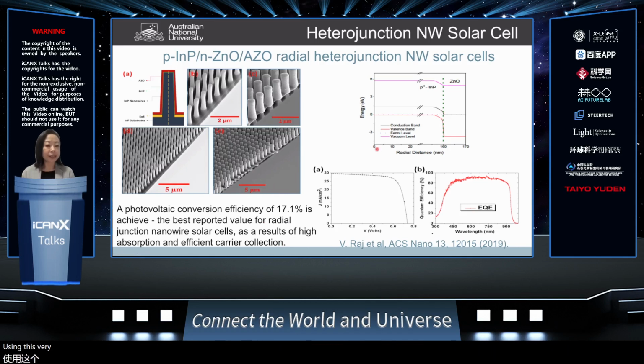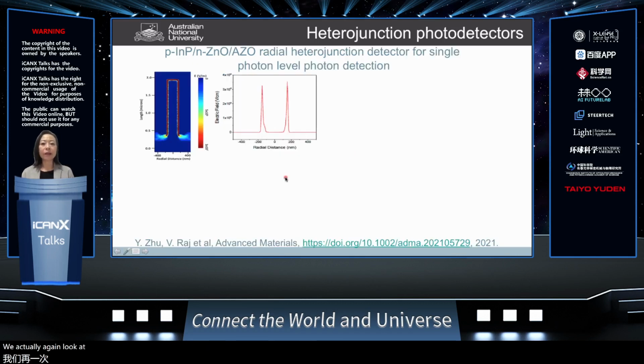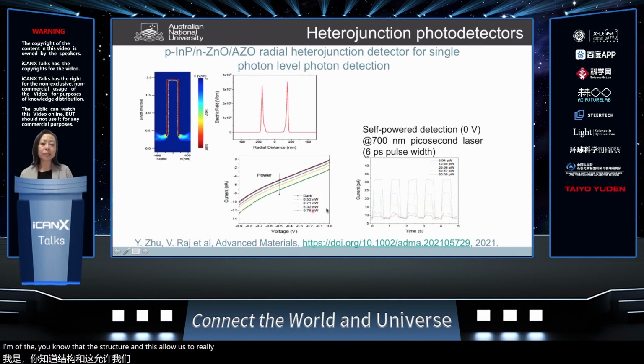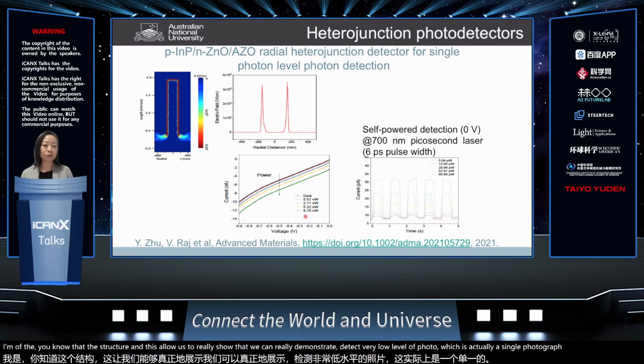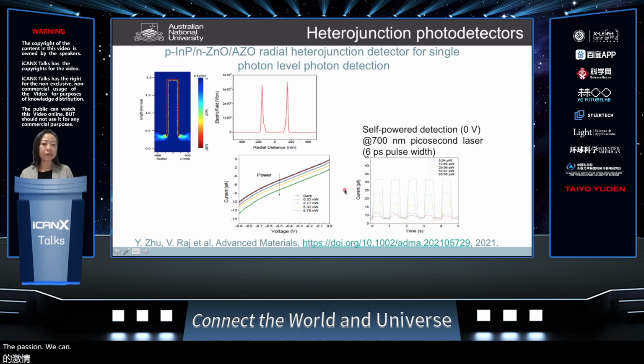Using a very similar technique, a similar device structure actually, we again look at their application for photodetection. If you look at the PN junction formed in this radial heterojunction, we found an extremely high electric field formed in a very thin interface region between the nanowire and the zinc oxide. This turns out to be extremely useful to reduce the dark current of the structure, and this allows us to show that we can detect very low levels of photons, single photon level detection we can achieve by using this structure.